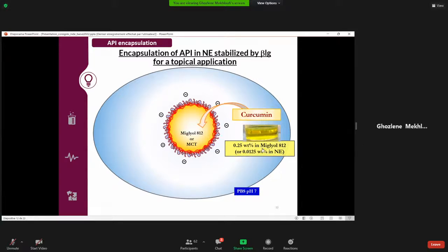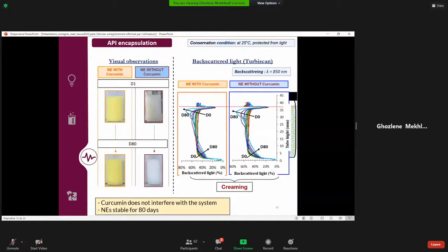And the concentration of curcumin here in the oily phase composed of Miglyol was fixed at 0.25% after an optimization study. So first we characterized the nanoemulsions: formulated with curcumin they appeared yellow, and without curcumin they appeared white. So we had two systems, and visually there was no phase separation observed in both systems, even at day 80 after the formulation. So both systems were visually stable.